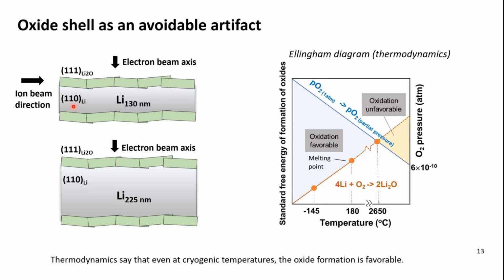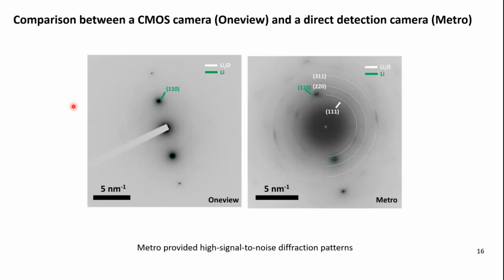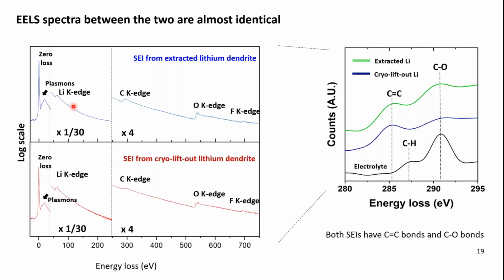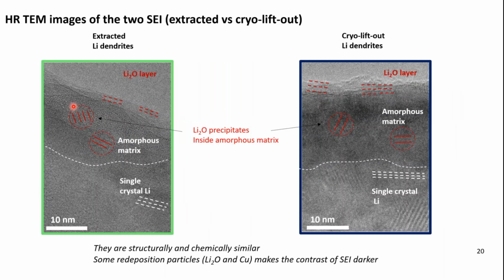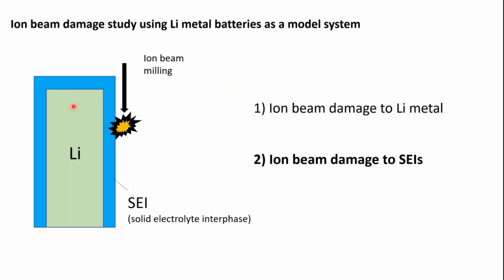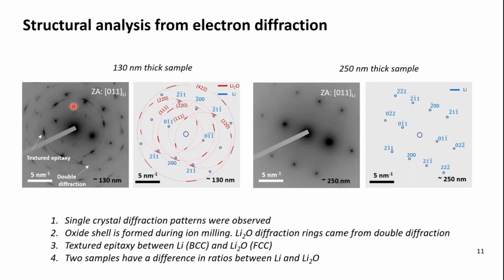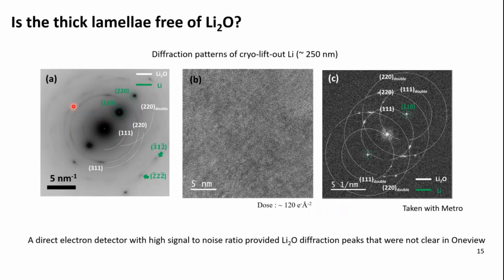What dose did you use for your imaging? What beam dose, electron beam dose? For imaging, oh yeah, I forgot to put that information. I guess there are two pieces to that, because I think maybe you showed TEM. Certainly there was diffraction, and then there was STEM imaging. Yep. So the dose rate for low dose imaging is around 10 electrons per angstrom squared per second, and the total dose is as follows.